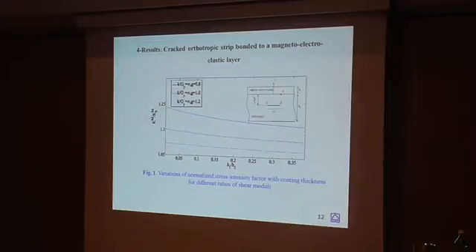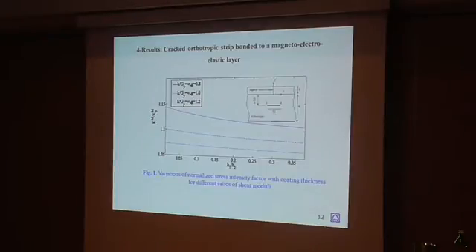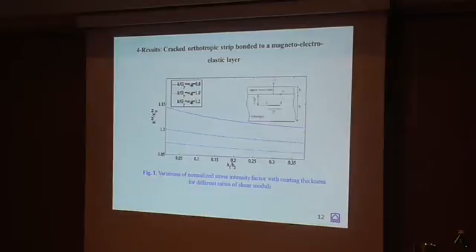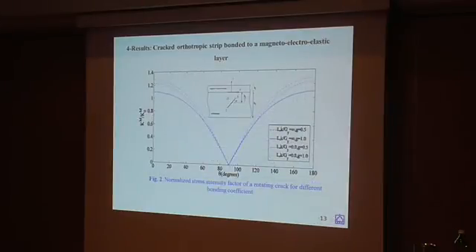As a first example, the variation of normalized stress intensity factor with coating thickness for different ratios of shear modulus is presented. As shown, when the thickness of the layer increases, the stress intensity factor decreases. In the next example, we solve the problem for a rotating crack under different boundary conditions.